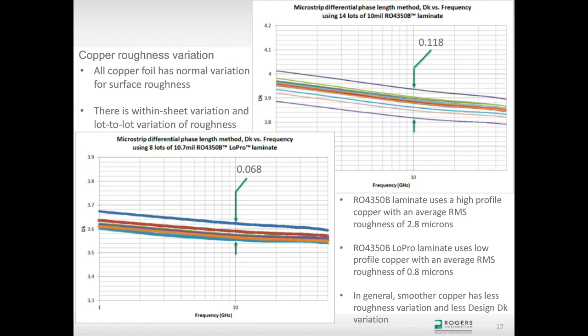Now, the bottom left chart is using basically the same substrate. It's RO4350B LoPro laminate, and the LoPro is basically a lower profile copper, smoother copper. And in this case, what we see, using the smoother copper, we see less variation, and it's just a natural thing. If the copper has a more intrinsically smooth surface, then it's just going to have less surface roughness variation. So for designs where phase response needs to be very consistent, then using a smoother copper is definitely a good thing to do because you have more consistency there.